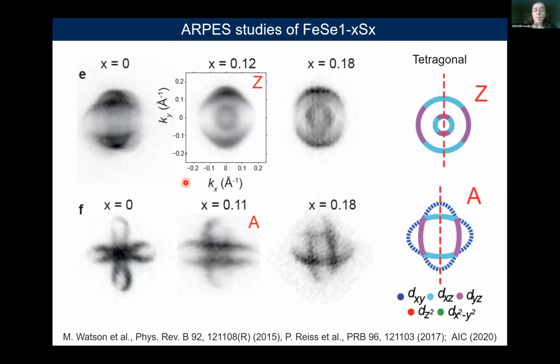And we can take cuts in the Fermi surface, and again, we can see that the tetragonal phase has this isotropic Fermi surface as we expect, and as the system goes towards low temperature, towards the iron selenium end here, this Fermi surface keeps distorting, and in the iron selenium case, due to the presence of two domains, we can see two crossed ellipses. Similarly here for the electron bands, this is what one predicts to happen, to have these two crossed ellipses. Indeed, these points will be separated by the spin orbit coupling, but it's very hard to resolve here. As we turn on the effect of nematicity, these bands become more elongated, and there's still a strong debate whether it is two ellipses or a single ellipse, and we'll hear later more from Luke on the effect of strain on the systems as well.